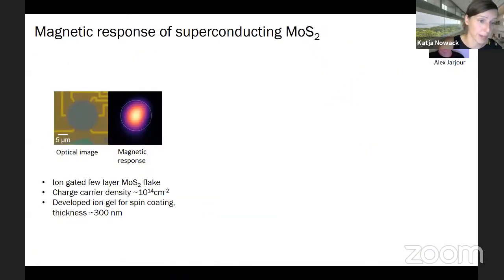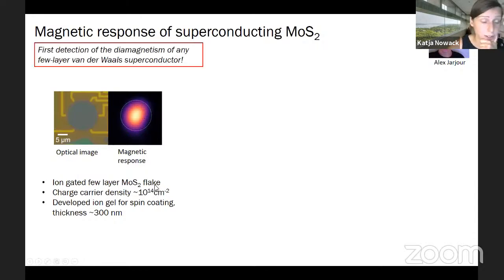But we've managed to create an ionic gate. We use an ionic gel that's spin coated on top of our devices, and that's about 300 nanometers in thickness, and we can look right through it. Here you see an optical image of a device. That's an MoS2 device, and here you see its superconducting diamagnetism. The spatial resolution here is terrible because the ionic gate is so fragile that we take any image from really far away. But we're not really after imaging here.